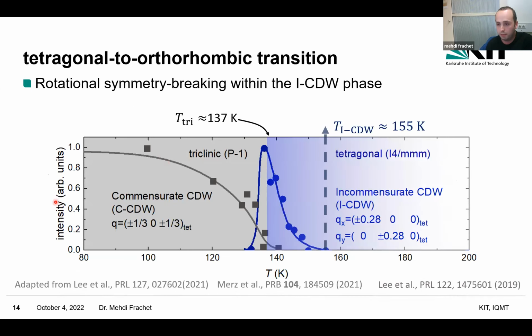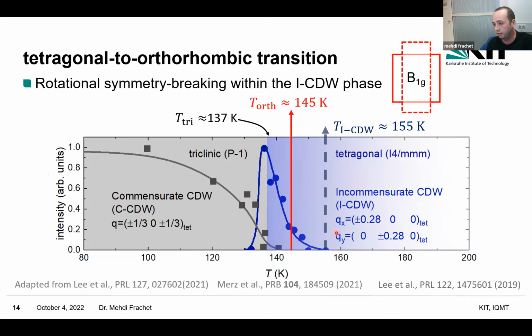Okay, so now to come back to this figure that you have already seen, what it means is that you see just below this strong enhancement of the incommensurate charge wave, you have this second order phase transition at about 145 Kelvin, which corresponds to a B1G orthorhombic distortion. Okay.